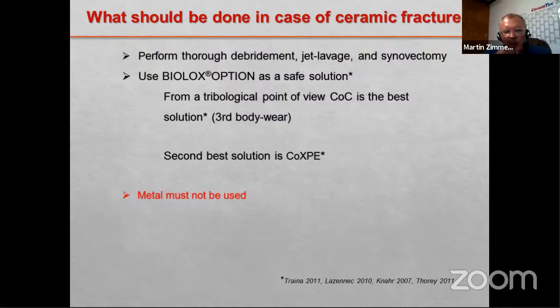We also have cases showing that ceramic particles remaining in vivo in the articulation become embedded in the polyethylene, but do not affect the scratch surface and scratch resistance of the ceramic. So again, and this is maybe the most important slide - speaking about the BIOLOX option after revision of a ceramic fracture - never use a metallic ball head as a replacement.